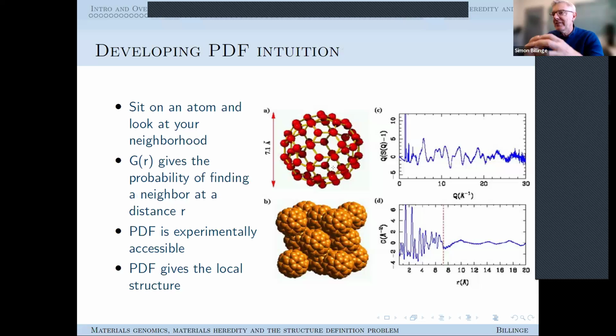That introduces curvature. And so then you have a mixture of 6 and 5-fold rings. And the 5-fold rings has the nearest neighbor distance and the second neighbor distance, but it doesn't have the third neighbor distance. So I can just do statistics on the relative intensity of the third peak to the second peak, and I can extract from that the relative number of 5-fold rings to 6-fold rings in my structure, for example. But I can also do the forward problem.